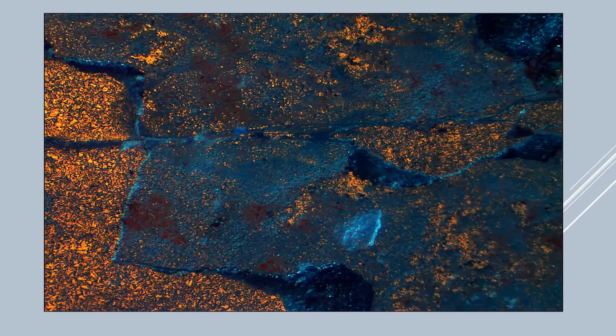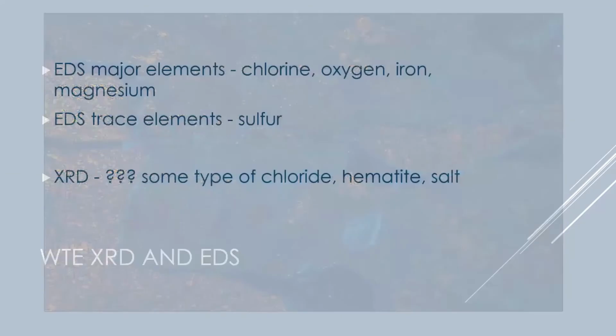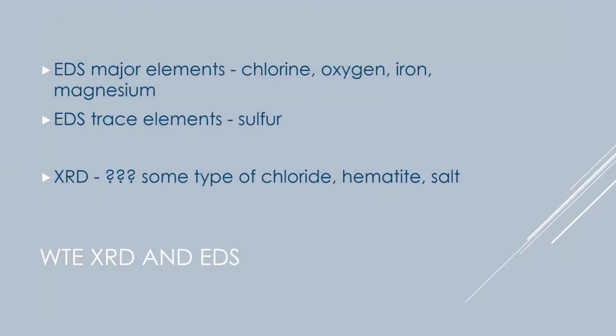Chlorine is a big problem. We're going to find sodium chlorides, all the metal chlorides. And what happens on these is that the deposits that get on these boiler tubes have low melting points, and they have incredibly high corrosion rates. When they first started making these waste to energy incinerators, it was sometimes up to about 1 inch per year. And of course, on boiler tubes, you won't even get through a year before all the boiler tubes are finished.